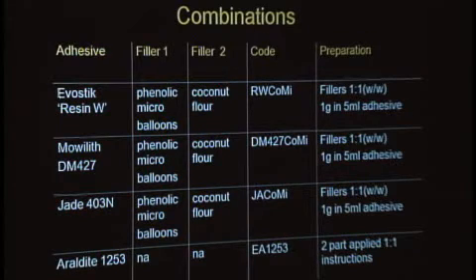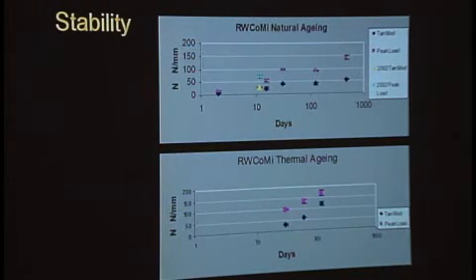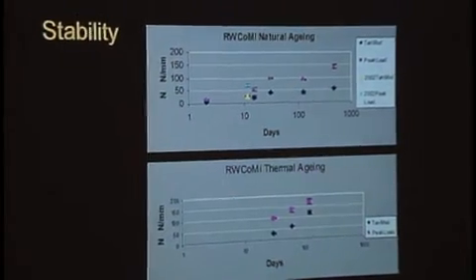So these are the combinations that we tested. There were the two mixtures, as I said, and then 1-to-1 mixtures of those two, weight to weight, 1 gram of that within 5 millilitres of our resin W. We did that for all those 3 adhesives, and then we used the Araldite as per the instructions, 1-to-1 part, as it has its filler already in there. I was going to talk about the stability of these particular gap-filling combinations. So this data is when we've used them as gap fillers. The blocks themselves were tested after mixtures of different agings.